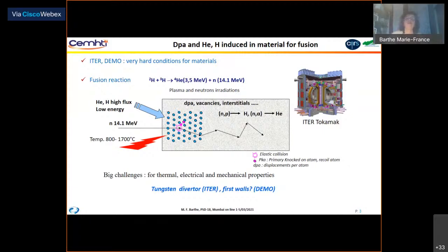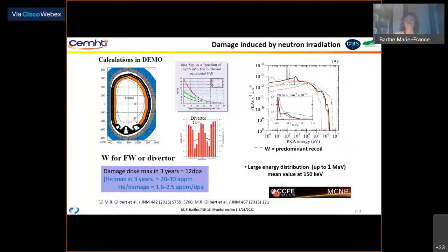This divertor is a key component. It allows to evacuate the helium ashes. And tungsten is also a candidate for the first walls in DEMO. So the damage induced by neutron radiation has been calculated in CEA, for example, and they show that the damage which will be created will depend on the position of the material in the tokamak, on the wall or the divertor. And for example, it can reach 12 dpa in 3 years in tungsten.